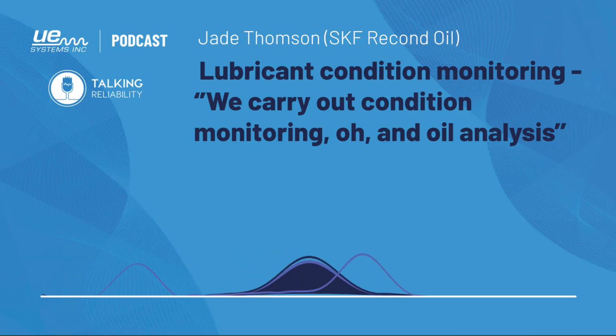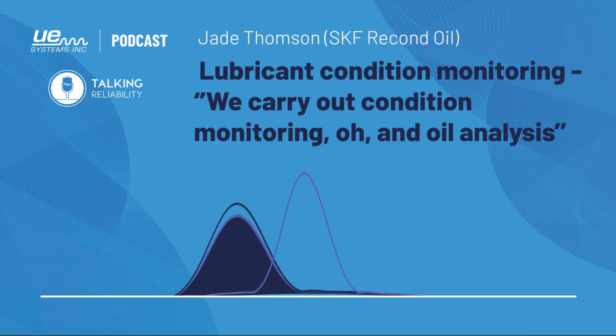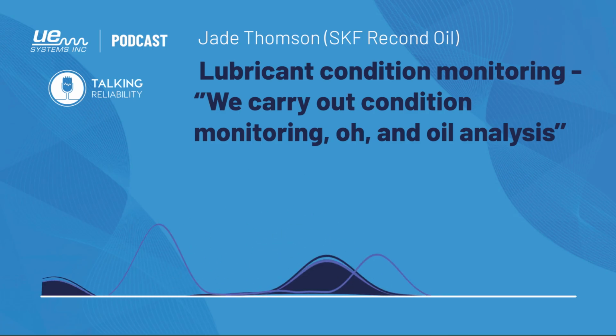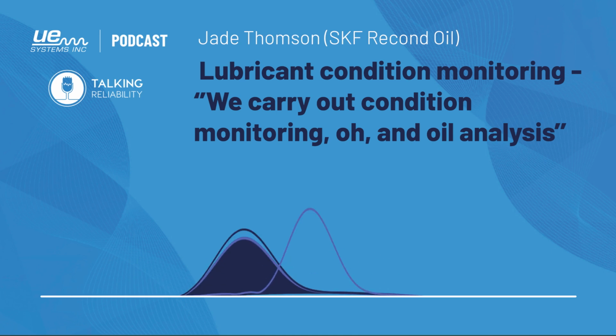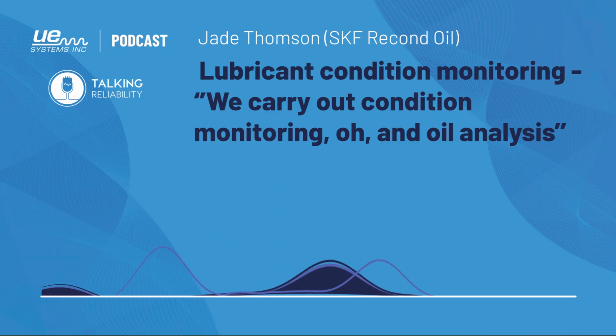Then suitability analysis. We looked at the hydrocarbons. If we're repeatedly getting an issue with viscosity of a lubricant, which is essentially its grade, or, I'll probably get shot for saying this, its thinness or thickness, its resistance to flow, how viscous it is. If we're constantly getting issues with that, it might be that we're shearing the hydrocarbons. So we do some suitability testing to understand, are we using the right grade of oil and do we need to change it?